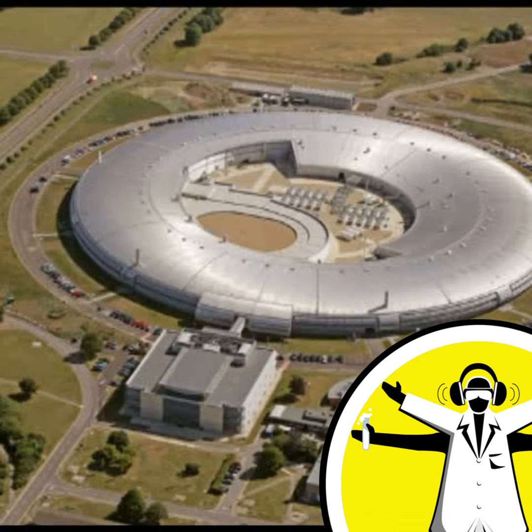And so what is the structure of green rust, and what have you been able to see about how it actually immobilises various contaminants? Well, we've been using X-ray scattering to characterise the formation of the structure, and what we've found is by using in situ wide and small angle X-ray scattering on I-22 here at Diamond, the formation reaction is a multi-stage process where we get an initial formation of very poorly ordered, virtually amorphous nanoparticles, and then the iron 2 adsorbs onto their surface, and this induces a recrystallization reaction which forms the green rust. We've also been adding contaminants, particularly uranium and selenium, to look at when these contaminants become immobilized during the formation process.